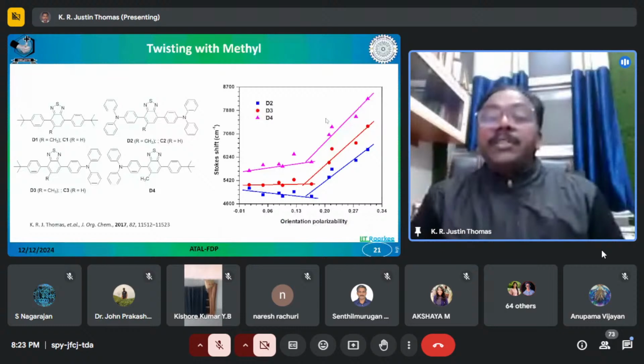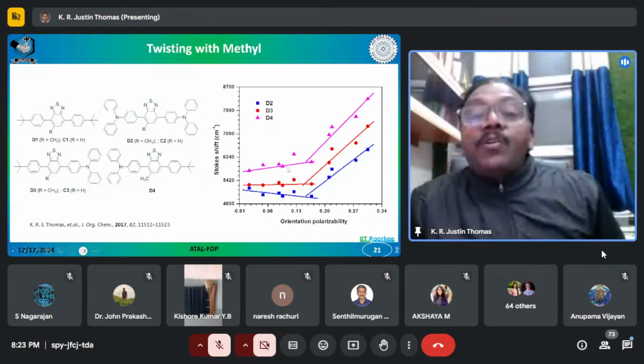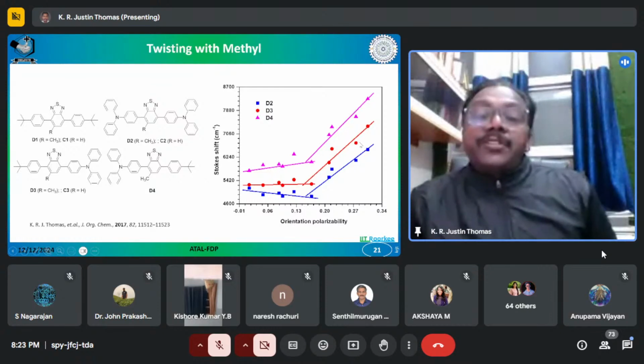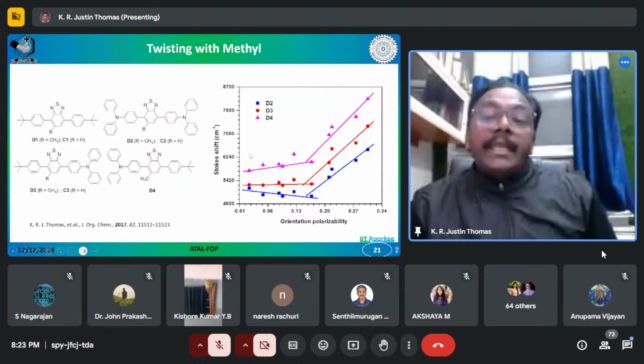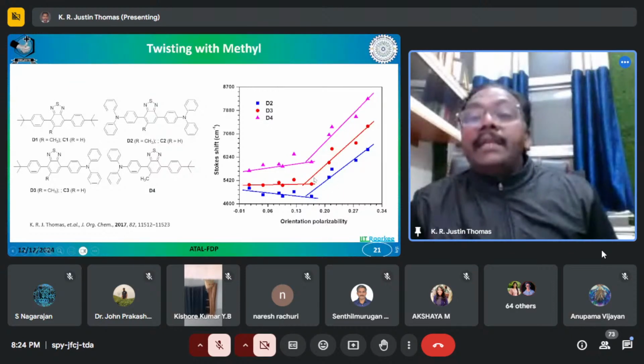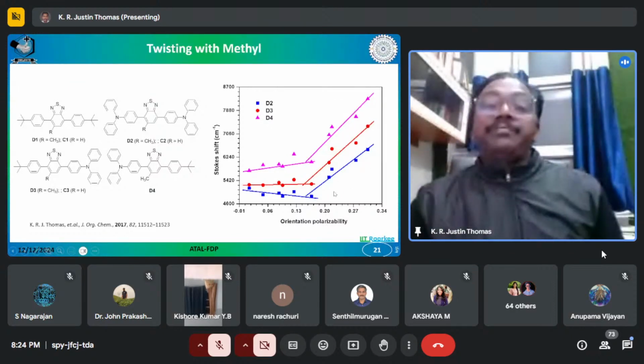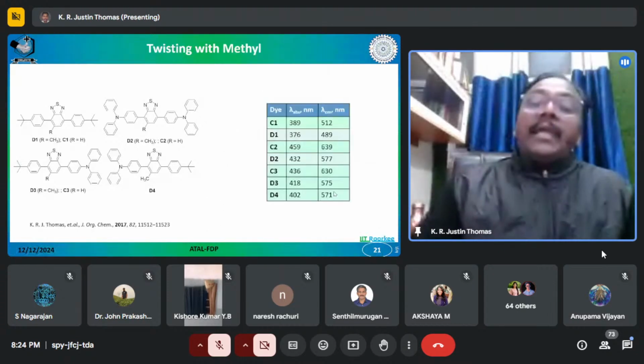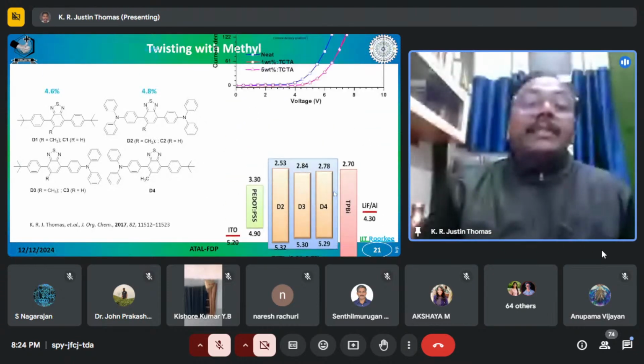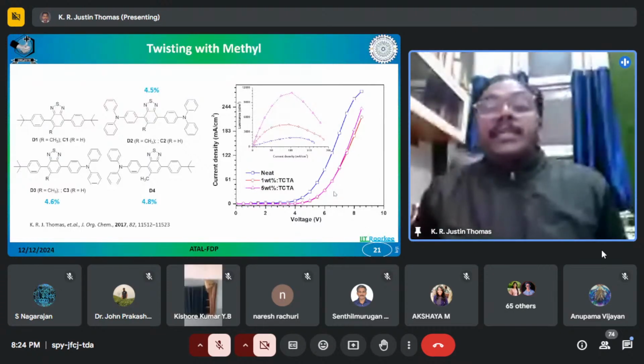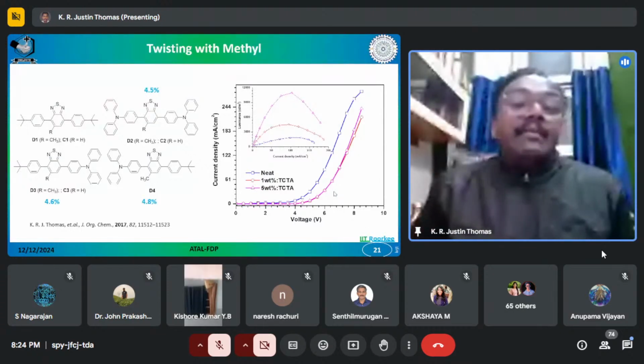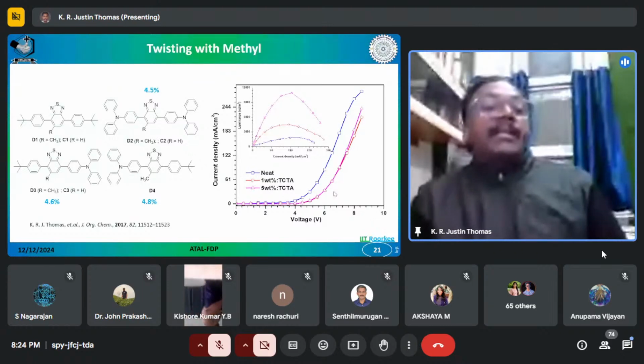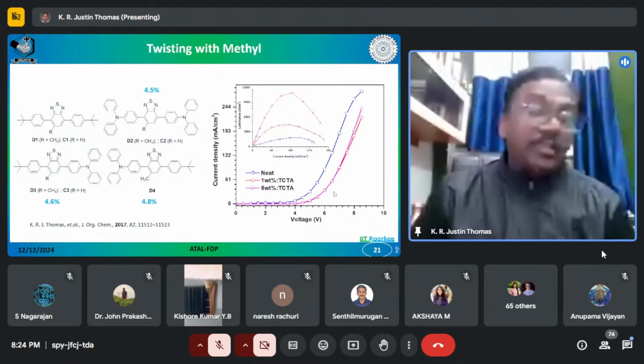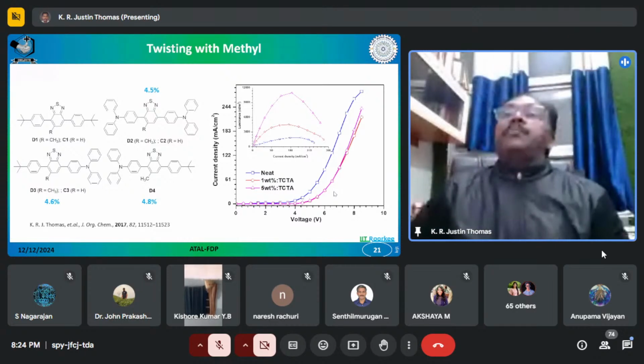How to confirm this one? You can do it by solvatochromism. And when you do the solvatochromic plot, you see that D2, D3, D4 are all having a bilinear relationship. Static non-polar region and steep slope polar region. Okay, so that led to a drastic effect as well in the efficiency of the LED devices. They are all having, not so great, but better than the common fluorescent molecules, which show efficiency around 2.1%.